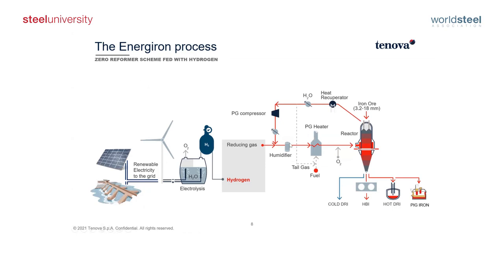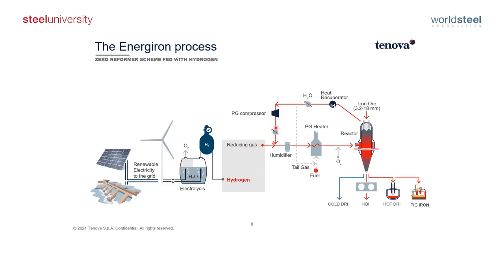meaning the scheme of the zero reformer module, that's our module. The reaction of reforming the methane into carbon monoxide and hydrogen happens entirely inside the module, using the very same pellets of iron that have been fed into the module as catalyst for this reaction. So inside the module is produced the reduction gas. We don't need, therefore, any external reformer, and the Energiron technology natively includes a scrubber for removing the carbon dioxide and the traces of hydrogen sulfide from the cycle.